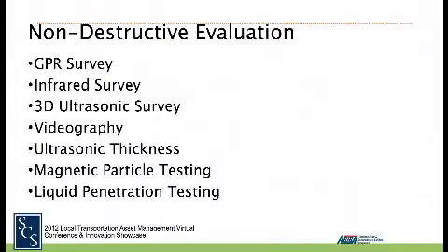But there are other tools that we are using now that are new, that help us, for example, ground penetrating radar. It helps us to find where your tendons are, the high strength steel, where are your rebars, how deep are they, and how much of deck concrete or substructure concrete is contaminated and or corroding, so that you can identify generally where your problem areas are, so you can quickly go to those locations to collect samples or to do specific tests to further define how bad is bad.